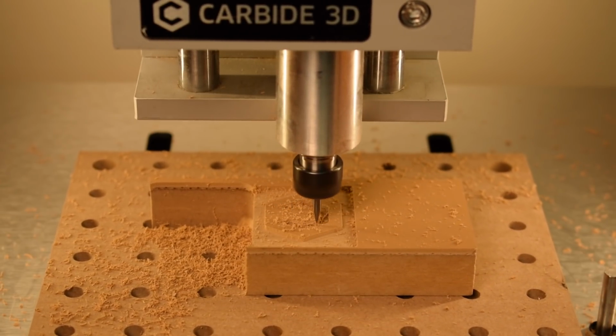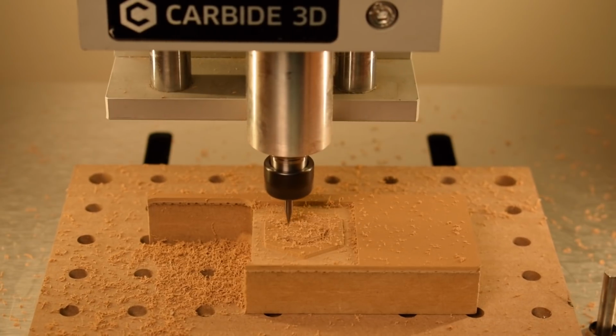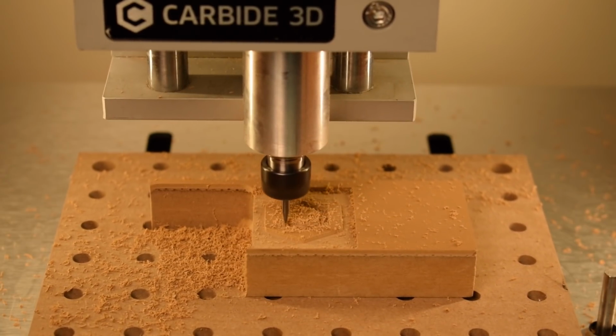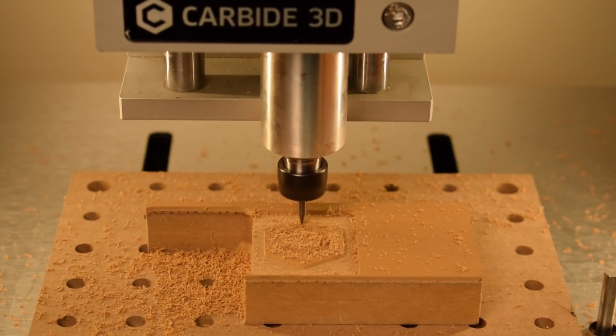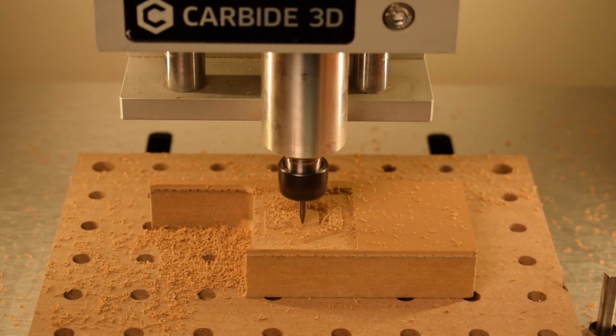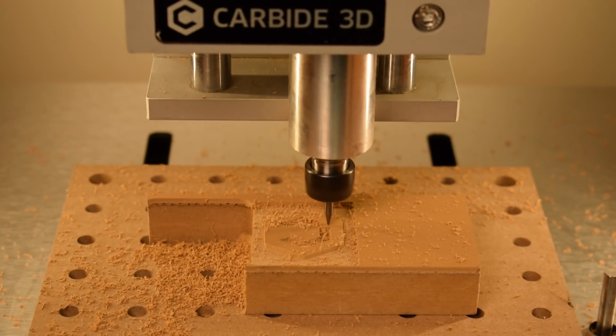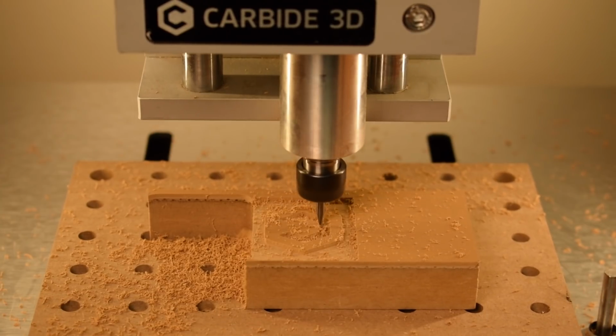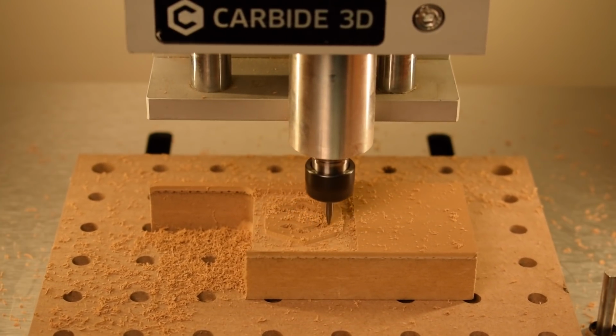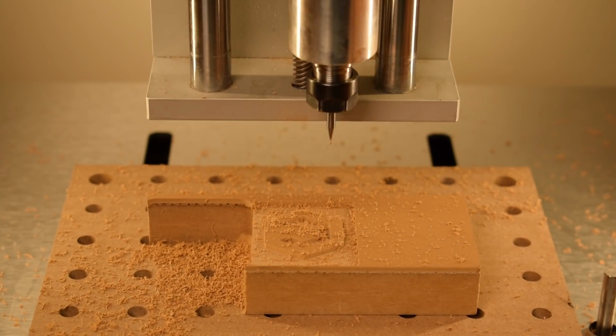My stock here is secured to the table with just some two-sided tape. Linoleum is soft enough that you could cut way deeper, but if you do that, your cuts tend to get packed with crumbly balls of linoleum. You're also imparting more cutting forces on the walls, which do flex a little bit. So if you want accurate, clean cuts, you should always aim to be a little gentler with your settings.